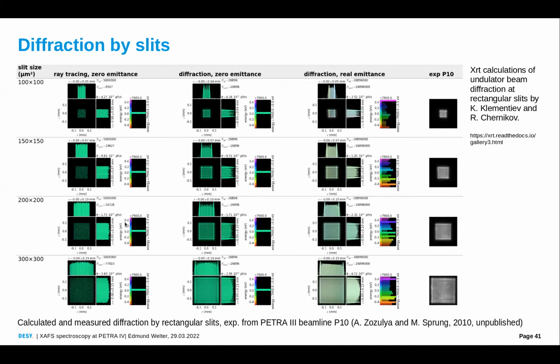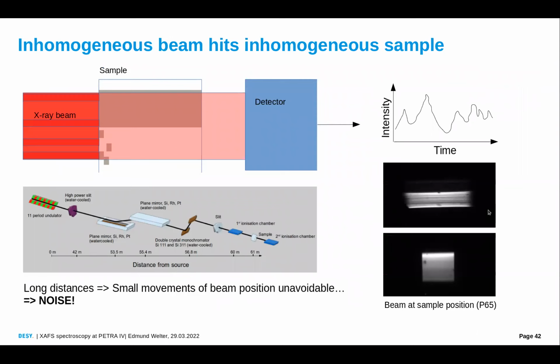And the drawback of this is that an undulator is a more or less coherent source. So we see all these artifacts which are caused by the coherence. We see diffraction from slits, etc. This is real, and these are calculations done with Konstantin Clementiev's and Roman Chernikov's XRT code. These are the calculations. These are observations at P10, another beamline which is optimized for coherence at PETRA III. We also see artifacts even with a short undulator at P65. You see all these stripes here, which are caused by diffraction on the slits of the beamline.